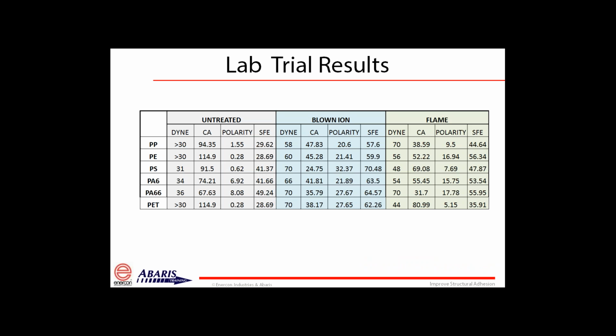So we've done a number of tests on a variety of materials, and what we wanted to talk about here was some basic, very common plastics that are used. Here, polypropylene, polyethylene, PET. You'll see that many of those start out with a very low dyne level, low to mid 30s, something where you're not likely going to get good adhesion. You also see a correlation between that dyne level in these cases and typically a contact angle above 90. You'll remember that Lou mentioned a contact angle above 90, you're not going to get proper wetting, and you ultimately are not going to get good adhesion. And you'll typically see lower surface free energy values as well. When you take those same materials and apply either blown ion or flame treating technologies, you see the dyne levels increase and contact angles by and large decrease, as well as surface free energies increase.